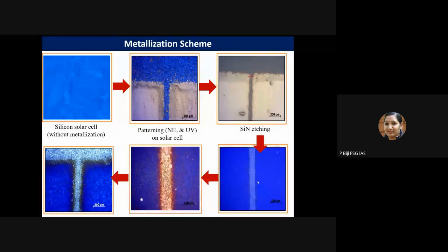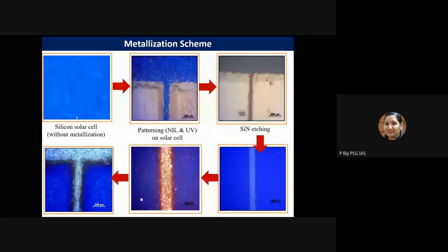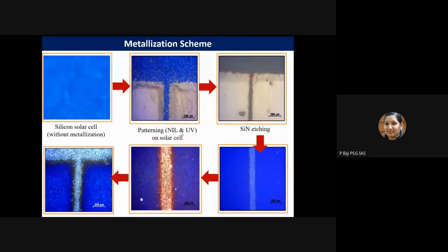So this is how we did the metallization afterwards. This first figure is the silicon solar cell without metallization. You can see only silicon nitride here. After that, we did the patterning using either nano imprint lithography or maskless lithography. That maskless lithography also is available in our institute. So if you want, you can approach us. Then after that, silicon nitride was etched, and then nickel electroless deposition was carried out. And after sintering, copper was light plated, and after that, a tin encapsulation layer was